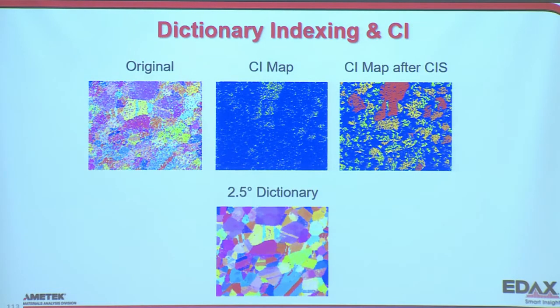Now, I mentioned how slow this is. Not slow, but it's just how time consuming it is. So here's what we can do. Here's our original scan. We know we've got some good data here. When we look at this, there's good data in the Hough results. So what I'm going to do is use the confidence index to identify the good data. So I've used the confidence index to do that, and I've indexed it with a 2.5 degree dictionary.